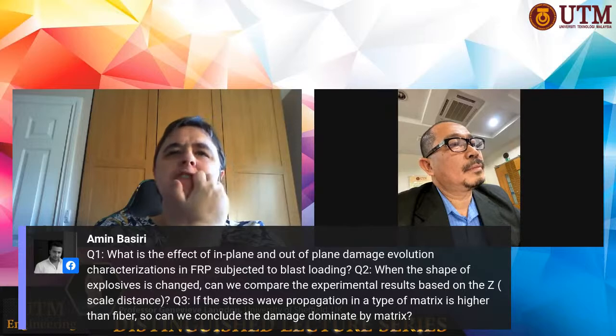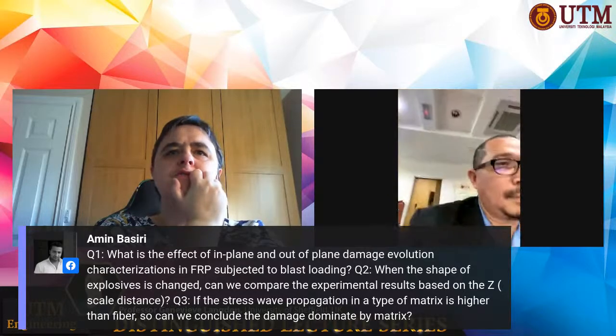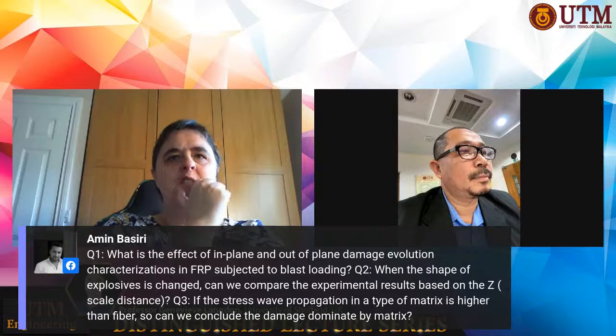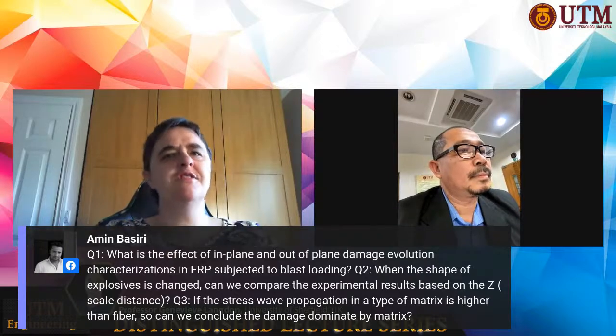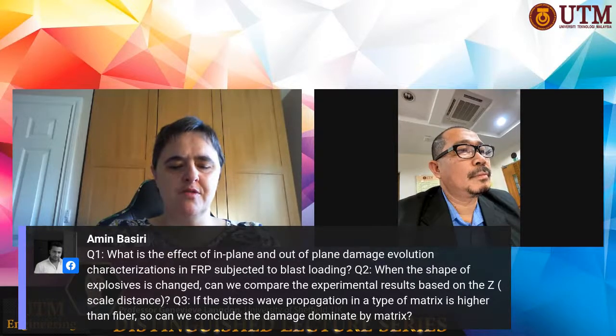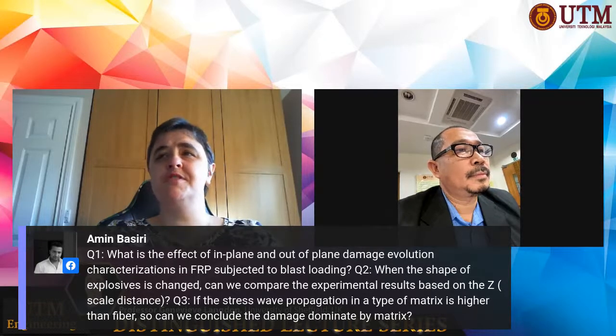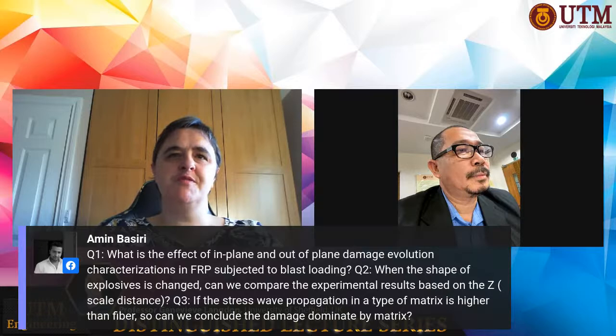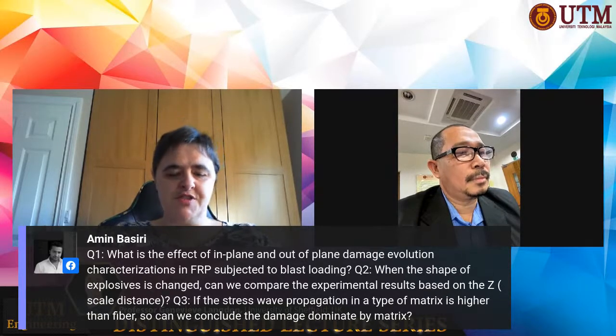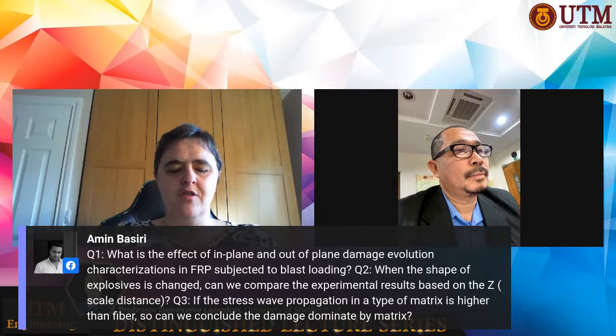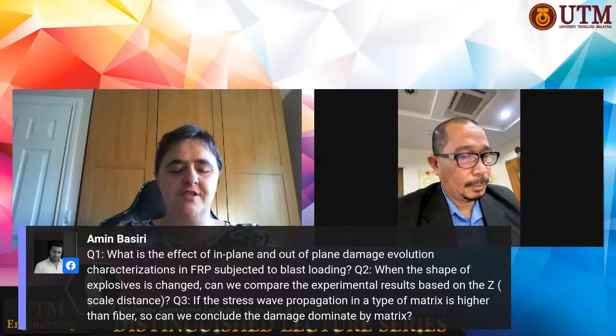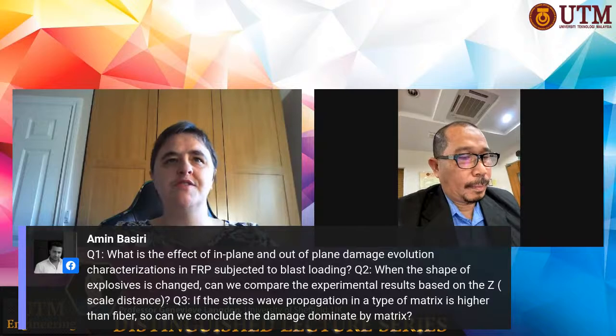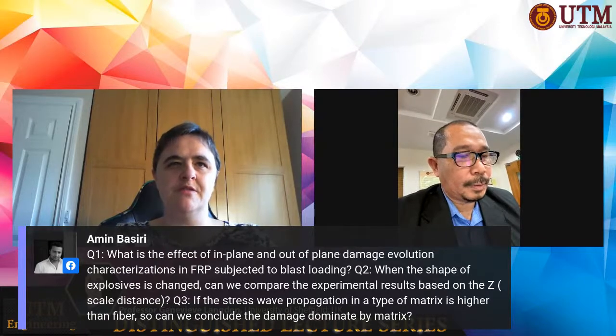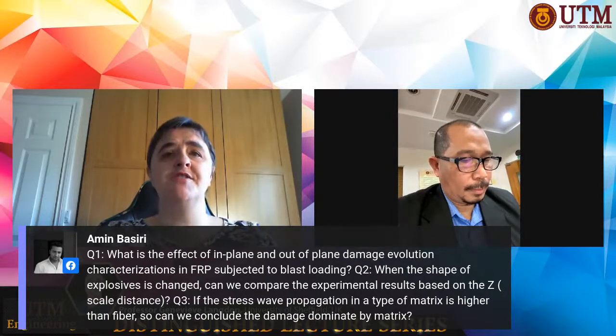I'm not really sure exactly what the question refers to. Most of the damage, so I've looked at the damage in a couple of ways. So the out-of-plane deformation of the plate, which is that midpoint displacement time history type response, we've looked at quite a lot. The in-plane damage, which is due to the stress propagation outwards from the location of the blast interacting with the panel, you can see in the delamination.